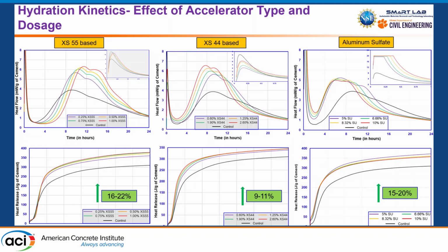And one more theory we have is that because this affects the rheology of your system, there's a polymer-based dispersing agent to distribute these seeds properly in the cementitious system. However, after that initial retardation, it behaves the best among all the accelerators, and we get a 7-day heat of hydration increase of 22% as compared to control.